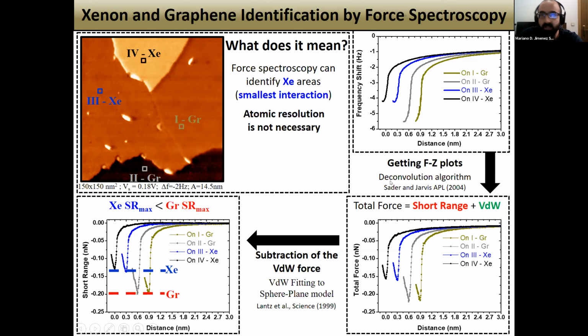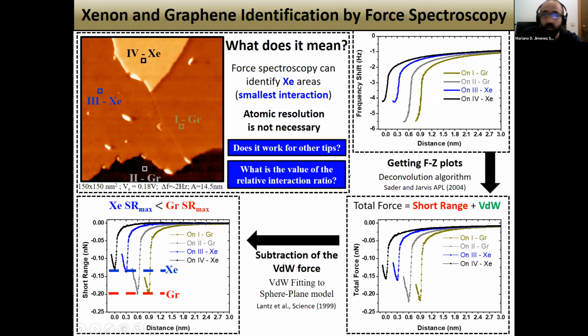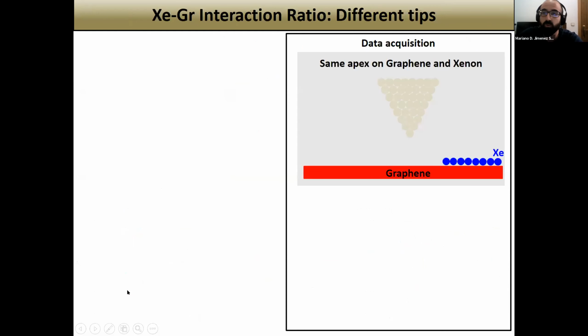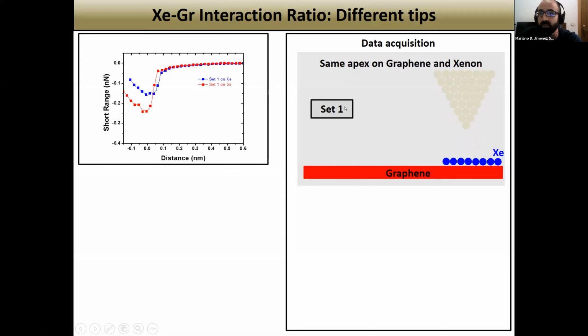Nevertheless, all this has been performed with the same tip apex. Does it work for other tips? And what is the value of this relative interaction ratio? I mean, of the difference. In order to answer that question, we have performed measurements with different tips on different regions. So we take a given tip, we acquire data on graphene and xenon regions, giving rise to a first set of data